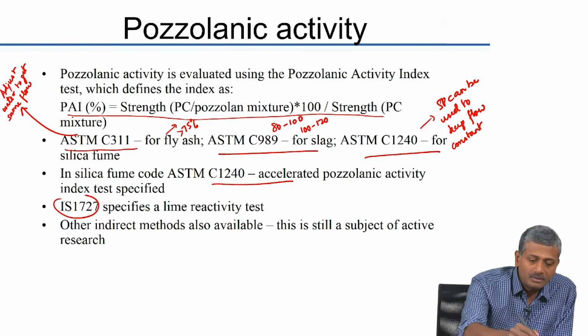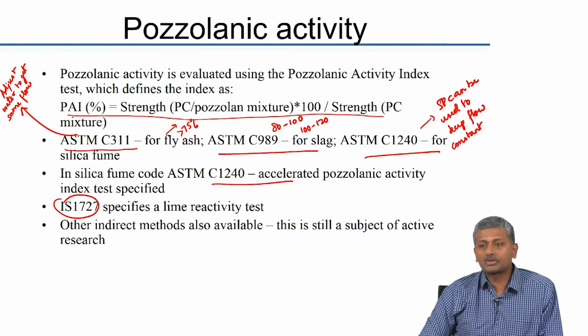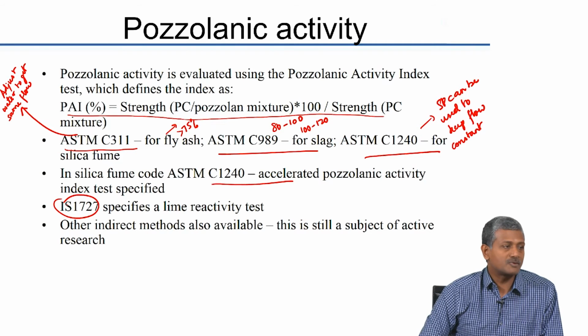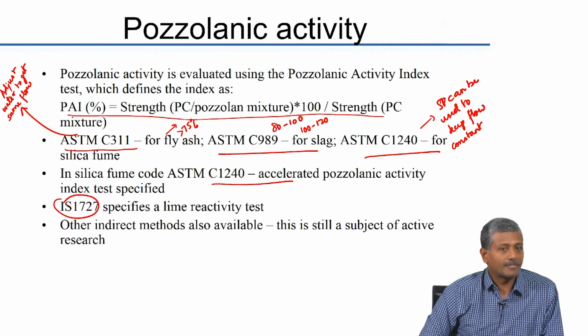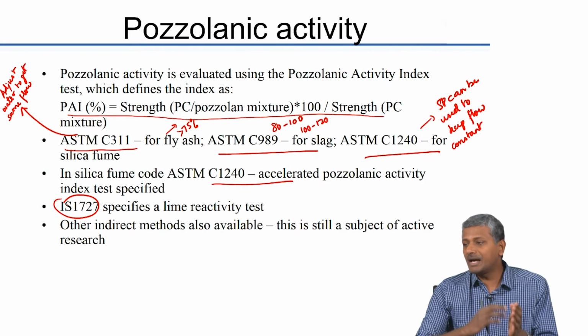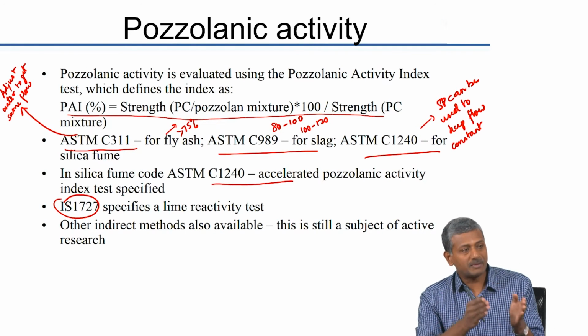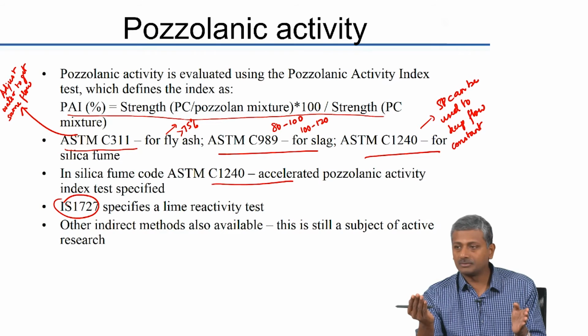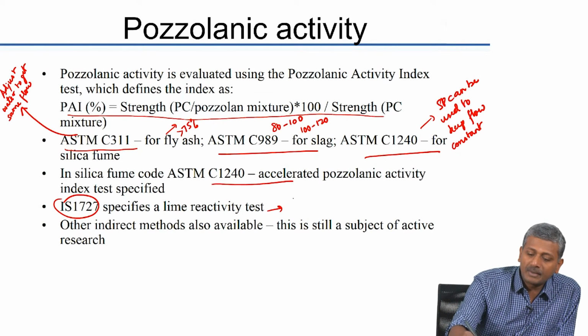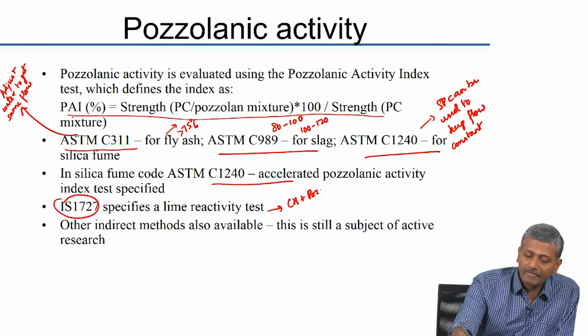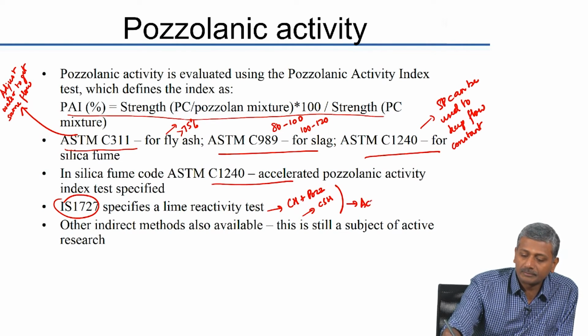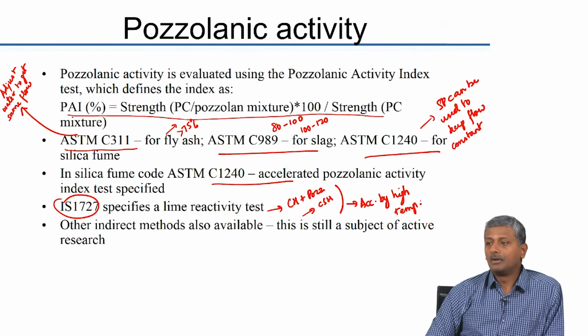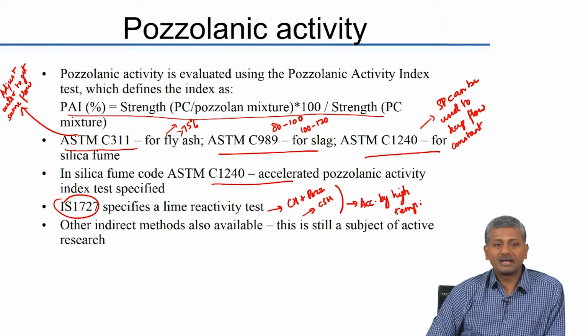Now, IS 1727, which is a standard which talks about pozzolanic replacements for cement, specifies a lime reactivity test. Please remember we talked about this earlier, that if you react the system with lime itself, it will still produce CSH. So, here you basically combine calcium hydroxide plus pozzolan, and that gives you CSH, and this reaction is accelerated by high temperature. If you look at IS 1727, that is the kind of reaction that they have. They directly react the lime with the pozzolan.